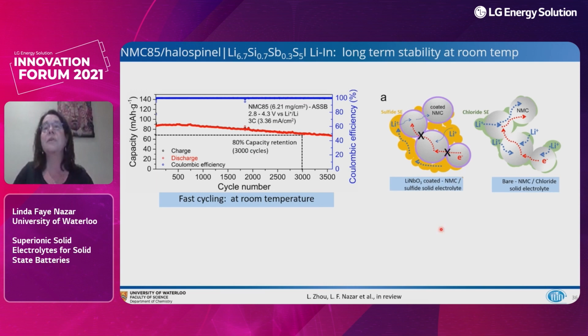And the reason that we think we see this good performance is that we don't have to coat the NMC particles with lithium niobate, which acts as a real hindrance to both ion and electronic mobility, because lithium niobate is not a good lithium-ion conductor at all. We now have this relatively limited case replaced with one where we have good electron transport and ion transport in the material, because effectively the particles are forced together.